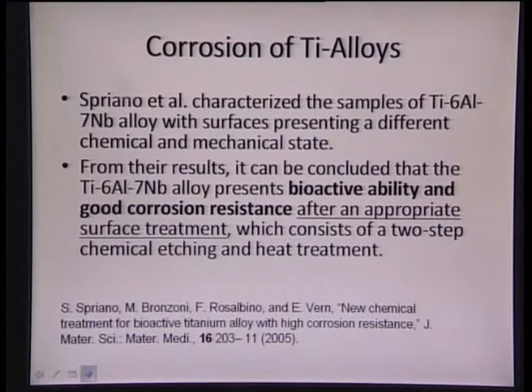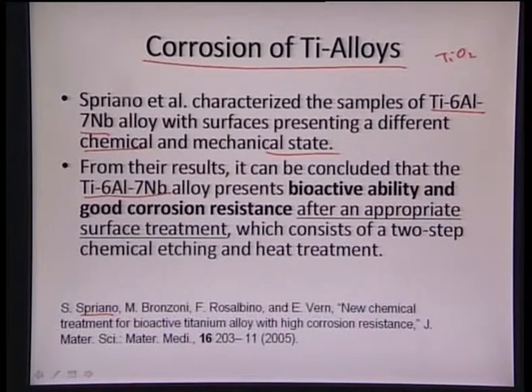And coming back to one more important property of this titanium alloy, its corrosion resistance. Corrosion of titanium alloys is also a very critical part, because generally we utilize titanium alloy, which tends to be good in corrosion resistance because of the formation of a TiO2 layer on its surface. There is a group of Spriano who characterized samples of titanium 6 aluminum 7 niobium alloy, with surfaces presented in different chemical and mechanical states, and they found that titanium 6 aluminum 7 niobium presents a bioactive ability and good corrosion resistance only after an appropriate surface treatment.